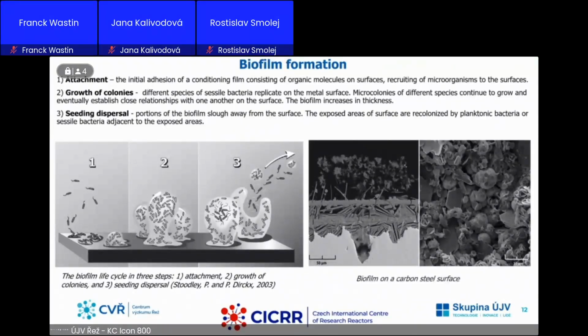You can see the life cycle of a biofilm in 3 steps. The first part of biofilm growth is attachment, the initial adhesion and conditioning film. The second step represents growth of colonies, during which the thickness of the biofilm increases, and the last step represents seeding dispersion that could lead to a secondary layer of biofilm, as you can see later. In the figure you can see a biofilm on carbon steel with local attack.